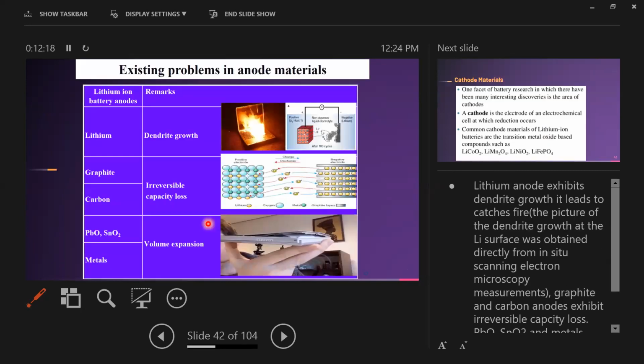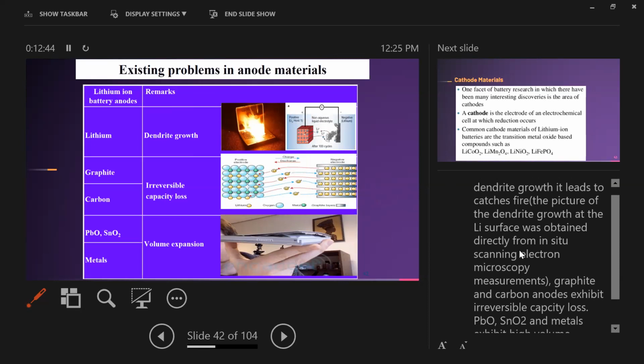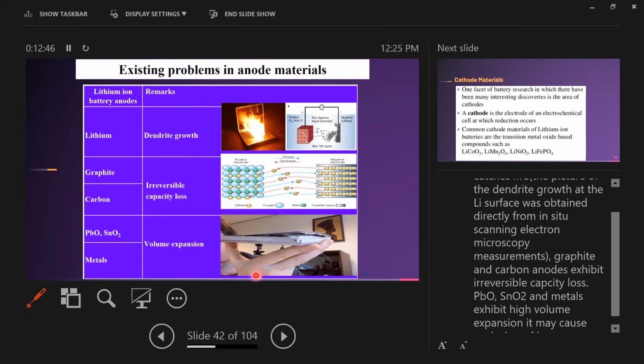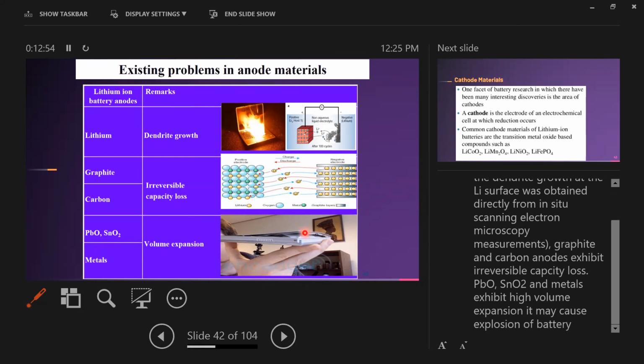And existing problems in anode materials are: lithium anode exhibits dendrite growth, which leads to catching fire. The picture of the dendrite growth at the lithium surface was obtained directly from in situ scanning electron microscopy measurements. Graphite and carbon anodes exhibit irreversible capacity loss. Lead oxide, tin oxide and metals exhibit high volume expansion, which may cause explosion of the battery.